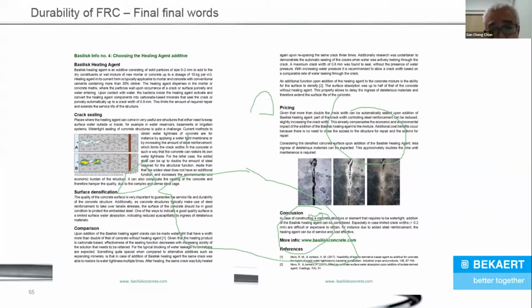And what is amazing about this product is this. Let's say you have a structure, a tunnel lining that is cracked up, and none of the cracks are more than 0.8 millimeter. So what do you do? You take 10 kilograms of this bacteria powder, mix it into water, and you spray it at the cracks. After several days, these cracks will start to heal by itself. It basically disappears, the cracks.